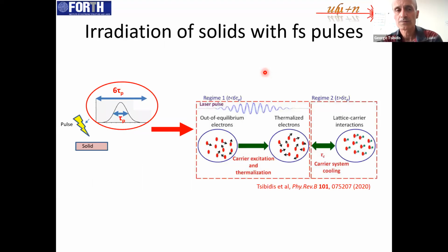So let's see first how the material responds when we irradiate the solid with femtosecond pulses. So this is the femtosecond pulse. This is the pulse duration. And we irradiate the material with a laser pulse. And during the pulse, we have excitation. I mean, the electrons absorb most of the energy because they have a much smaller heat capacity than the lattice system. And they get excited. So in the beginning, the electrons reach an out of equilibrium state, and through electron-electron scattering and also some electron-phonon scattering, the system starts to thermalize the electron system. So this process takes place within the pulse or even a bit later.